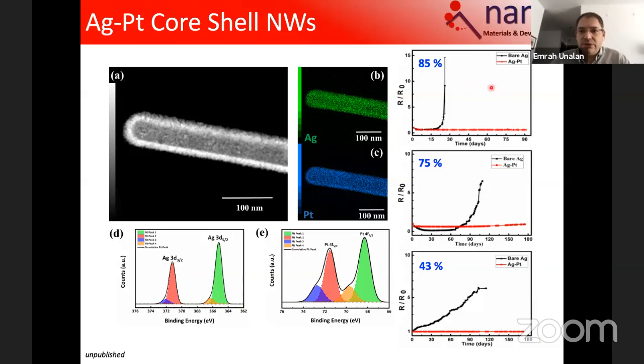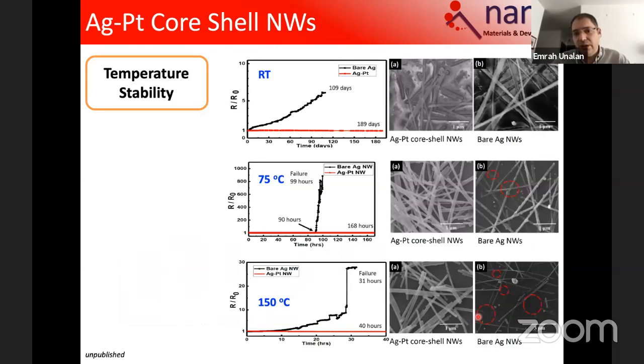And as you see, these plots are, forgot to write in here, but this is 85% relative humidity. This is 75 and this is 43. As you see in all cases, the bare silver fails, but in striking contrast, the platinum deposited networks are very highly stable. Temperature-wise, the situation is the same. Room temperature, the bare one dies in 3 months almost. I mean, at exaggerated temperatures, as you see, even 150 degrees C in like 10 hours start degradation. But if you have platinum-coated nanowires, degradation is not prominent at all.